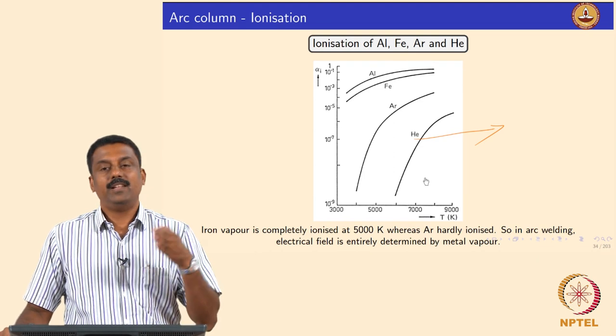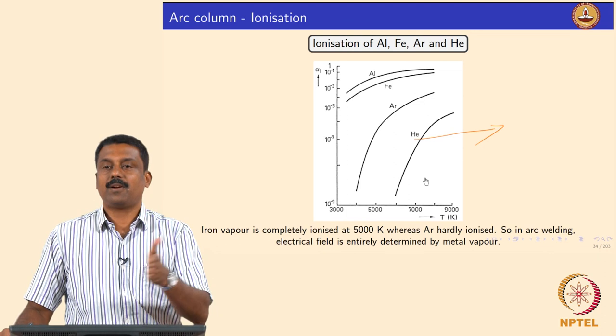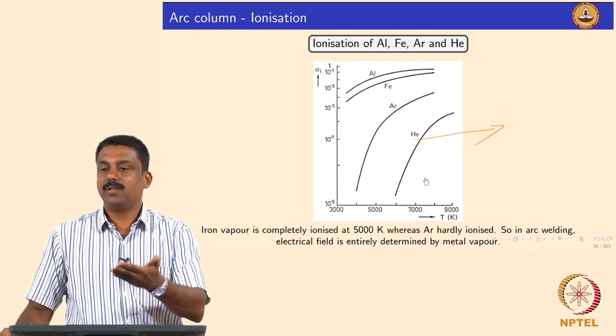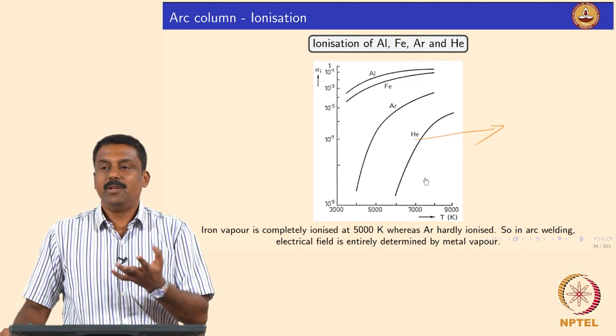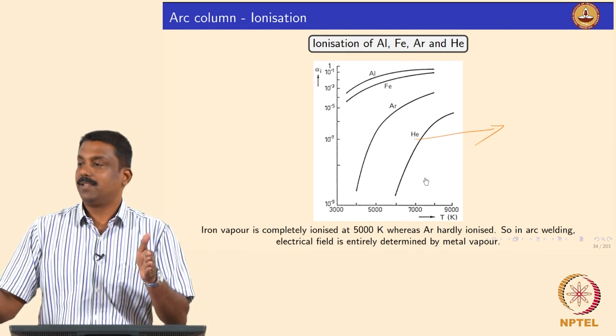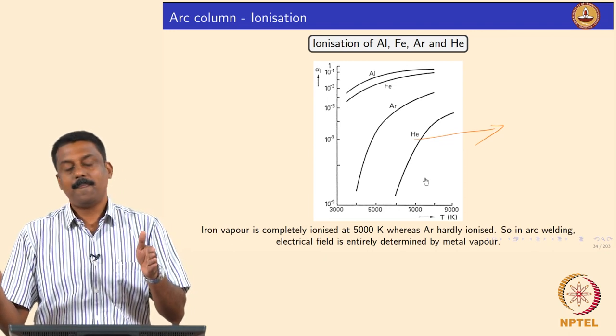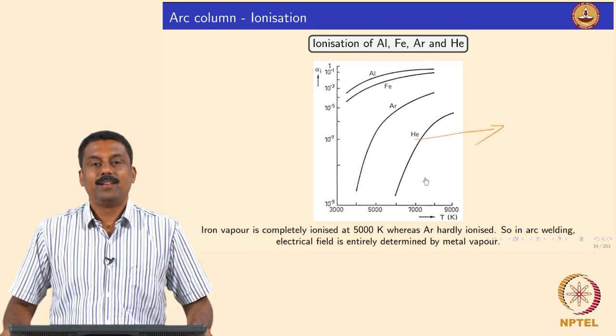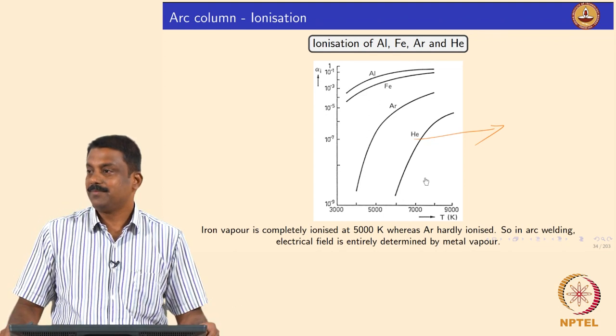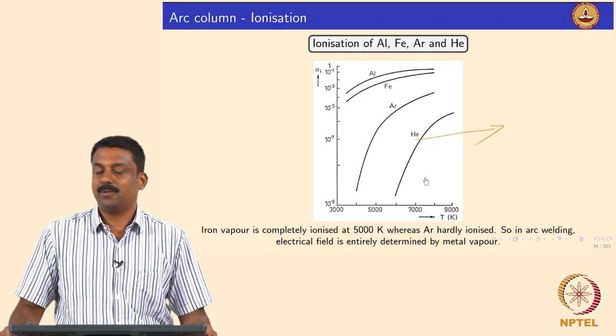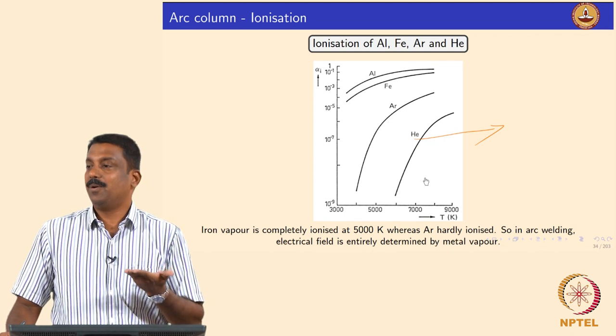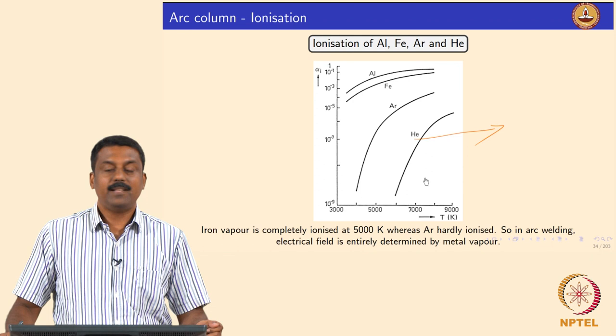Discharge can be sustained because of this ionization process. The ignition is by thermionic emission; the moment ignition happens, electrons reach the gas medium and upon gaining the ionization energy EI, electrons are knocked out creating helium ions. An avalanche of these reactions develops enough charge carriers, and conduction from cathode to anode strikes the arc. The moment you strike an arc, you also melt the anode. If you keep your tungsten electrode as the cathode, you will start melting the anode.